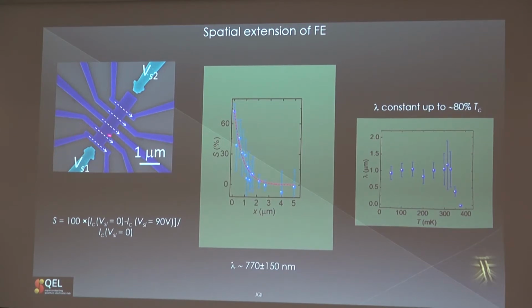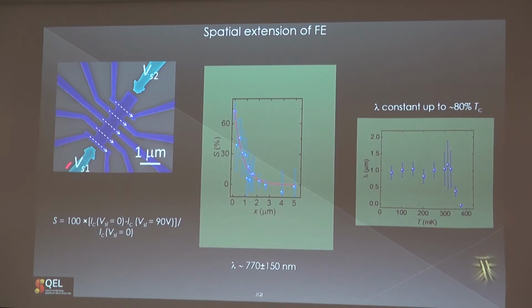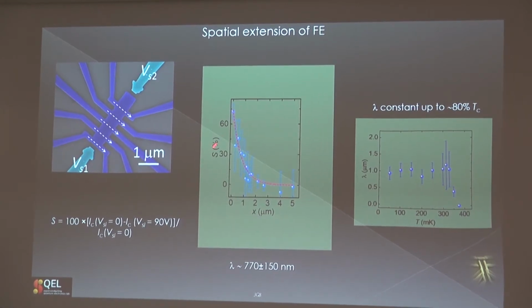And then the idea was to study the supercurrent in these wires by applying different voltages. By fixing the voltage, you see how it's damped by moving from this gate to the other gate, okay? So we define the attenuation parameter as the critical current without gate minus the critical current with some specific gate that suppresses a lot of supercurrent, in terms of percentage, okay?